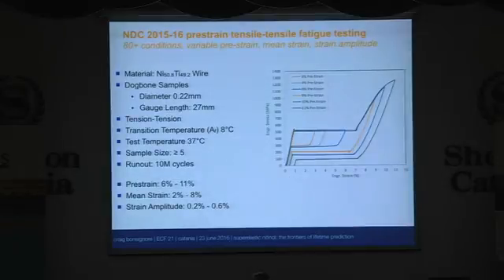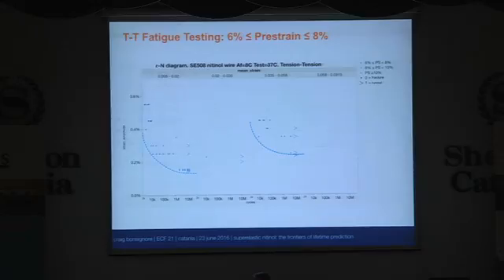So we've done a bunch of testing on tensile samples. The characteristics are here, where we vary pre-strain, mean strain, and strain amplitude. And what we see is that we can see this influence. So right here, we're looking at the low pre-strain group, and I've taken the basic SN diagram and binned it out here by different levels of mean strain. You can see basically where we're at there. And then if I go to the higher pre-strain levels, you can see that as we increase the pre-strain, my threshold is increasing. So we're actually getting a benefit in the material by increasing this amount of tensile pre-strain, which is kind of confusing, but it's very clear that it's actually happening.